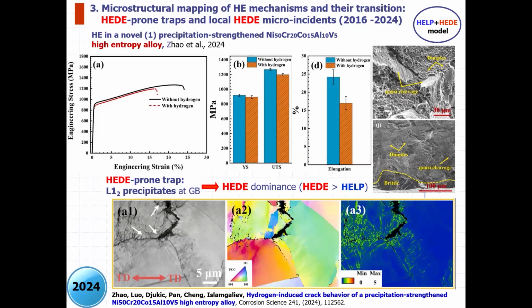This is the brand new result. As you can see, we investigate the novel precipitation strengthening high entropy alloy, which has L1,2 precipitates at grain boundaries, which is also typical for steels and nickel-based alloys, and provides very good ductility and very good strength of this high entropy alloy. But as you can see, we have a very high susceptibility to hydrogen embrittlement. We have a ductility drop here after hydrogenation in this slide.